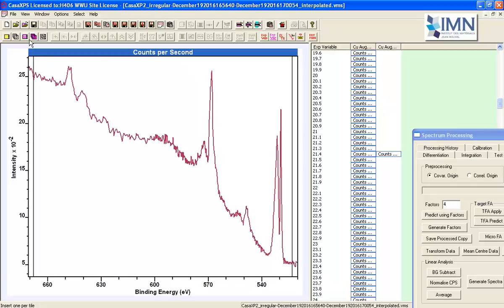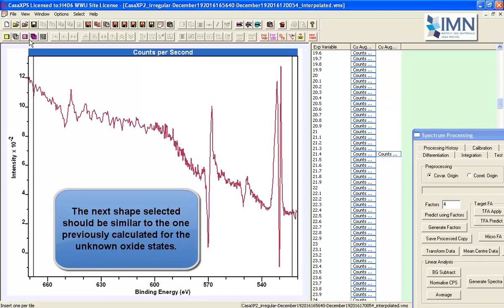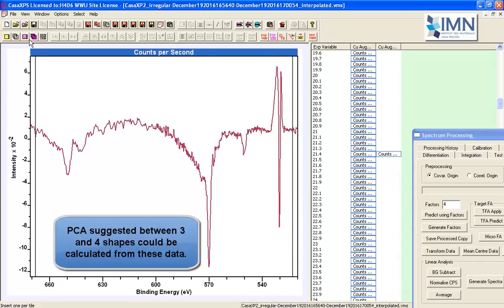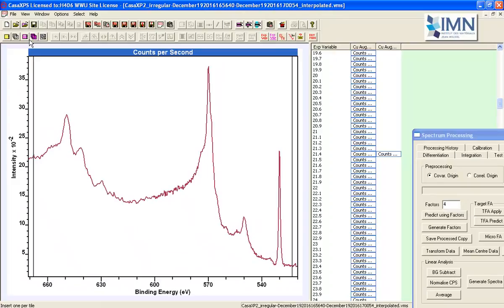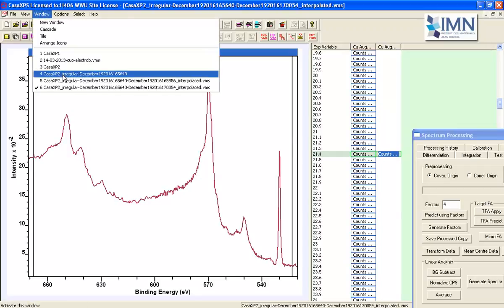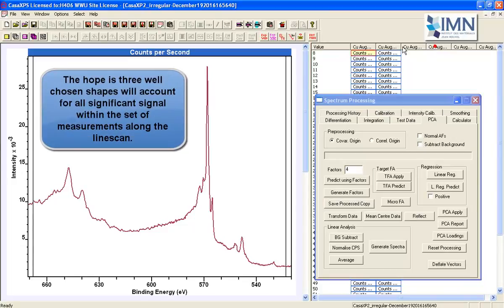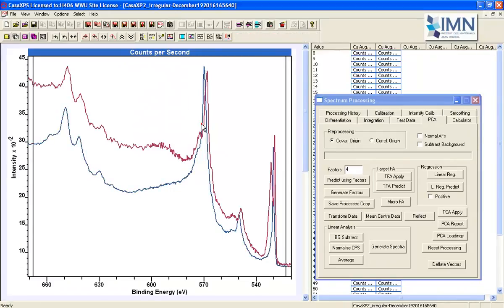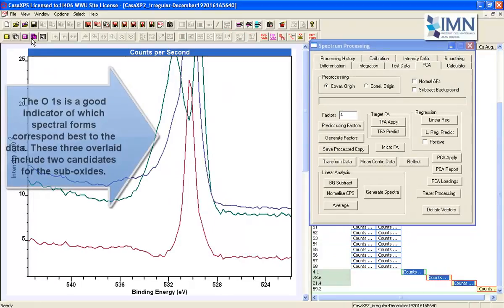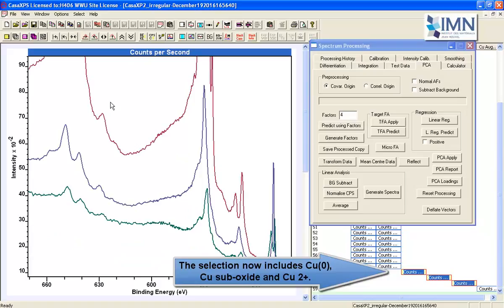Having chosen a Cu²⁺ reference, we look at what this same calculation does for the interpretation of the suboxide. We step through past the influence of the Cu²⁺ and try to remove an amount of Cu²⁺ from the suboxide we selected, coming up with an Auger line shape that should be very similar to the one calculated from the metallic copper and the copper(I) suboxide. Having done that, we copy these through to the original data set and do a comparison to make sure what we've done makes sense. We need to select three line shapes from the four to use as basis functions to reproduce the original data.